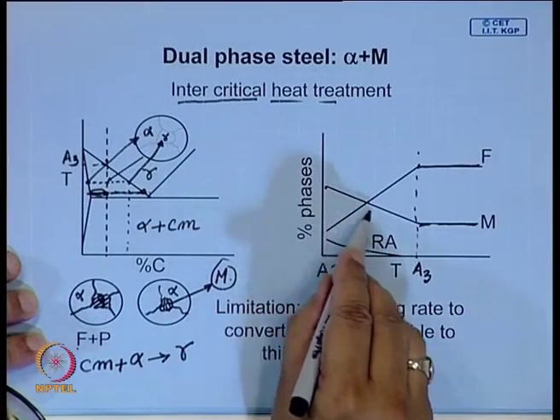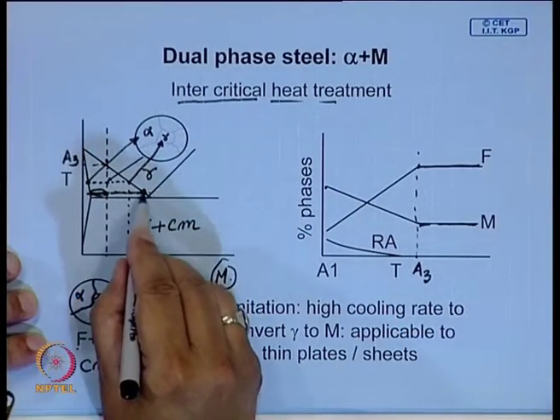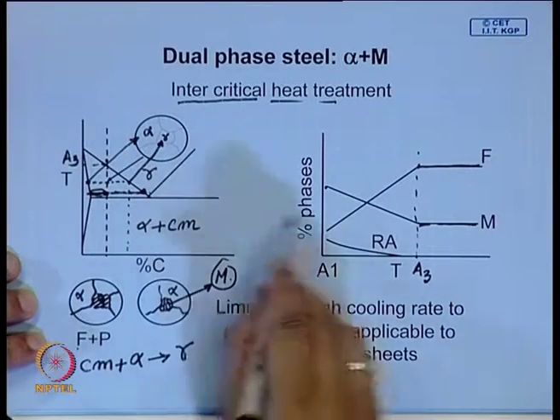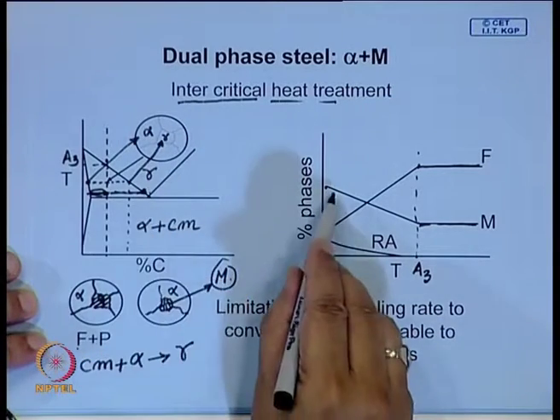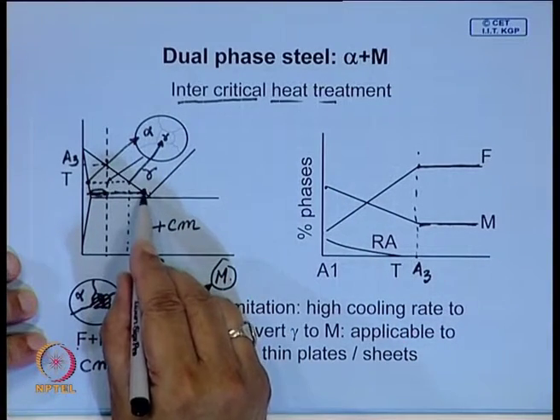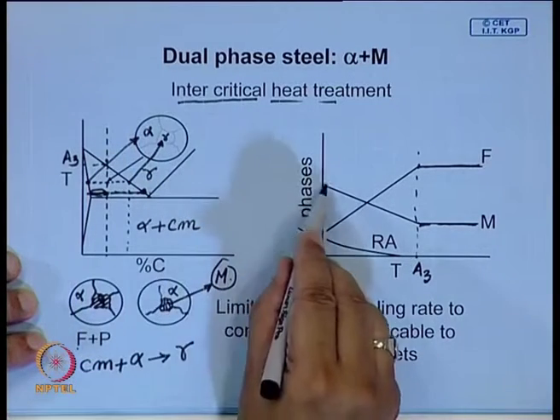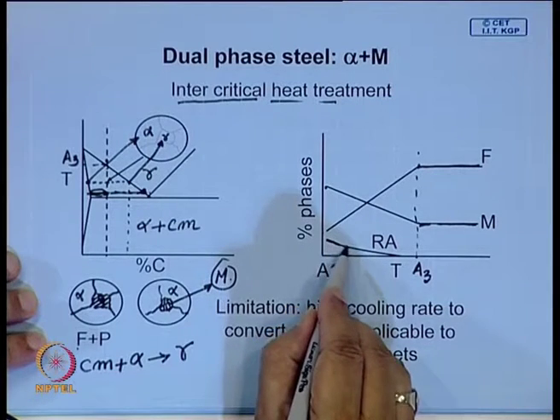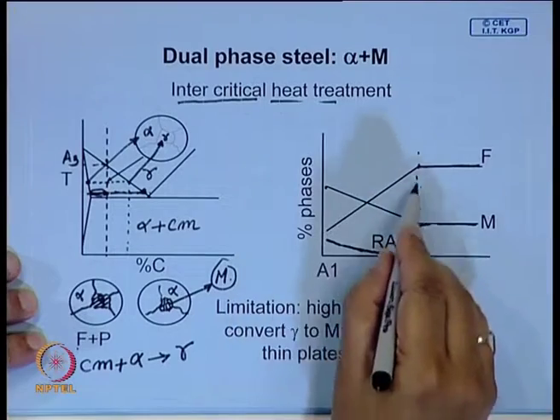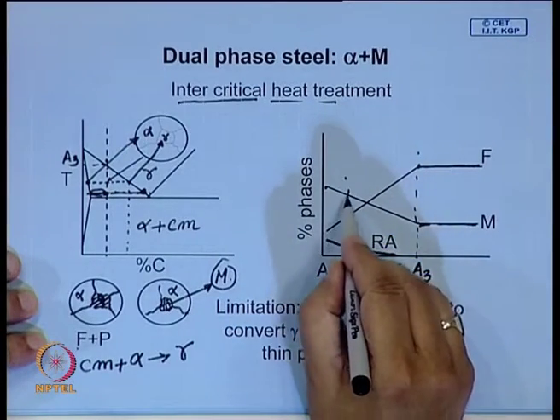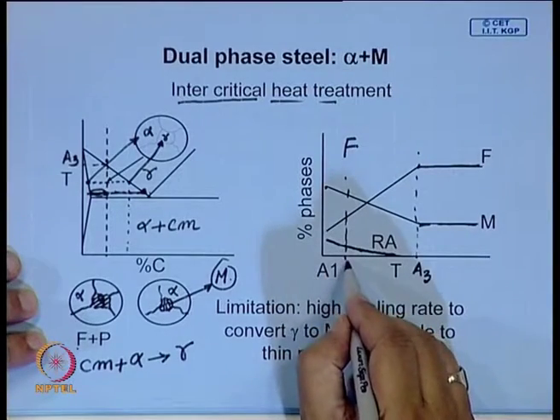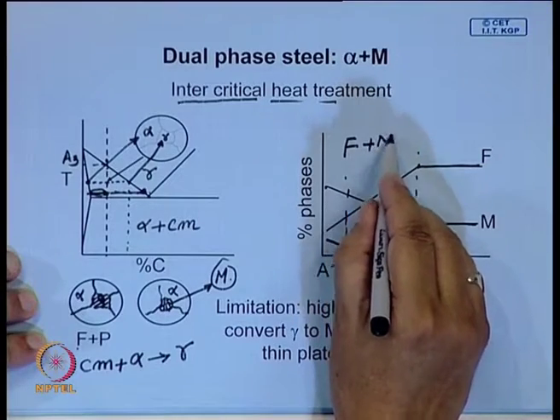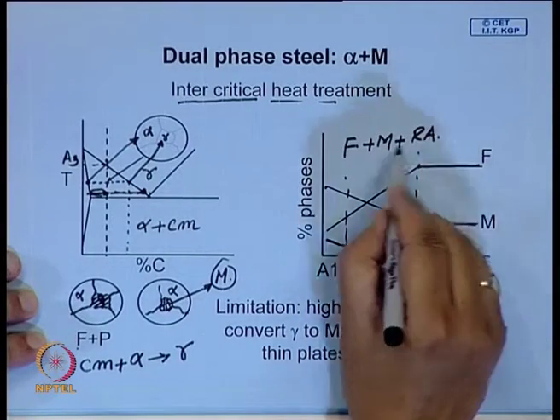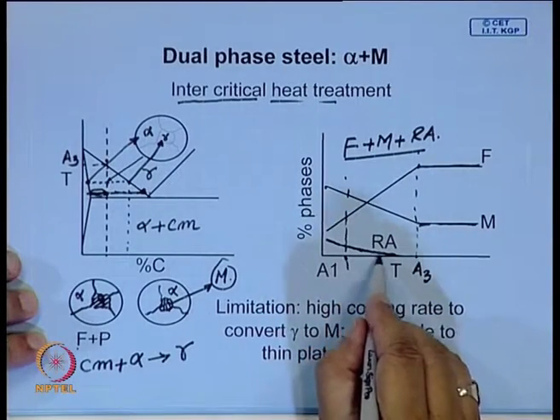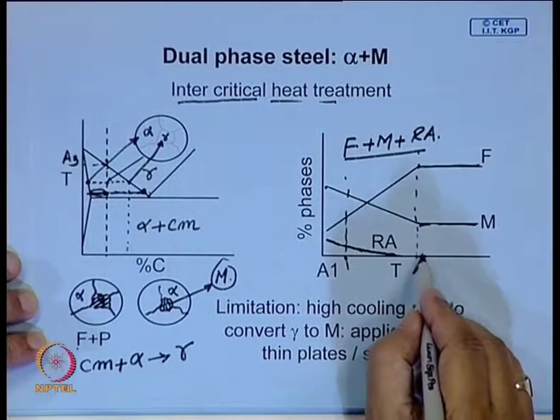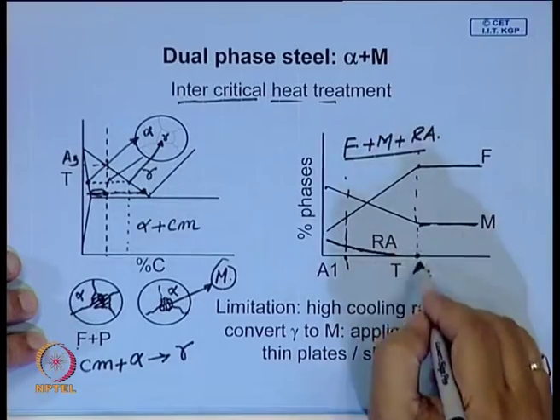As you go up, that amount of martensite will change, and this martensite will have a much higher carbon content. Therefore, its MS temperature is likely to be lower, and MF certainly will be lower than room temperature. So, even if you quench, you are likely to get some amount of retained austenite, and this goes on decreasing. So, your total structure, if this is the intercritical heat treatment temperature, will be ferrite, martensite plus retained austenite, and as you increase the temperature, the amount of retained austenite goes on decreasing, and here of course, you will get ferrite and martensite.